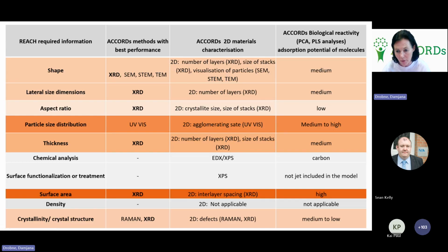So we try to describe it not in terms of size distribution, but perhaps more in some size of flakes or something. So we don't know which descriptors best describe the shape of the material. So it's not just a shape, but the terms are a little bit different or adopted to 2D materials. And this shape has a medium contribution to the adsorption of molecules. Then lateral size dimension, XRD is the method of choice. Again, we talk about number of layers, again, medium contribution.